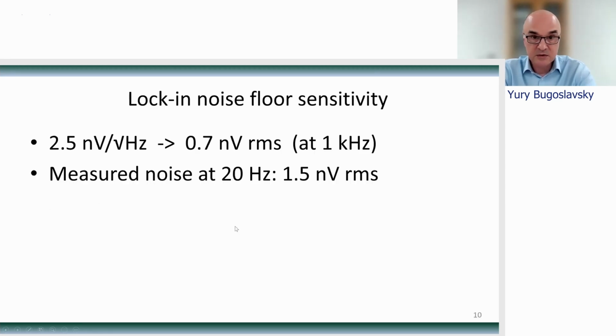Let's compare this to the sensitivity of the lock-in amplifier. The specification tells us that it is 2.5 nanovolt per root hertz, and root hertz is a convenient way of expressing the base sensitivity independently of the bandwidth. If you convert it to the noise we can measure using the settings I spoke about in the last slide, we get to 0.7 nanovolt RMS noise, and that is at 1 kilohertz measurement frequency. We measure at 20 hertz, and the spec is slightly less here, and we get 1.5 nanovolt rms. If you compare it with the previous 0.7 nanovolt, we see that the coils we're using are very well matched to the input parameters of the machine we're using to detect the signal.